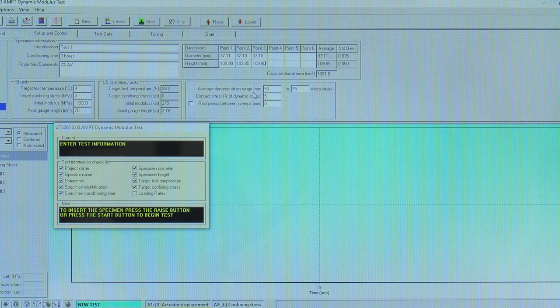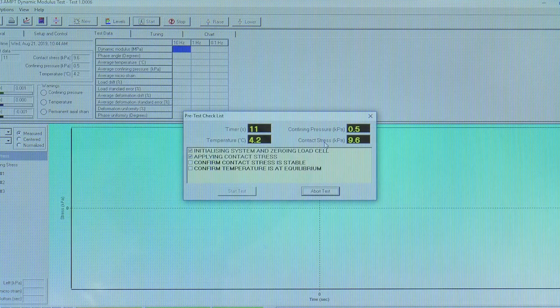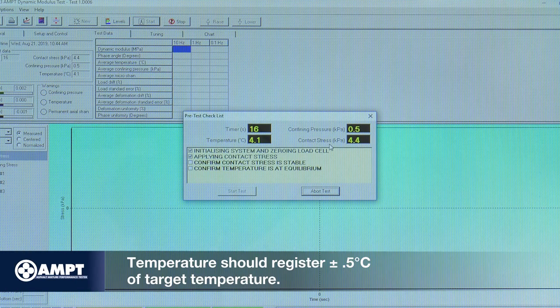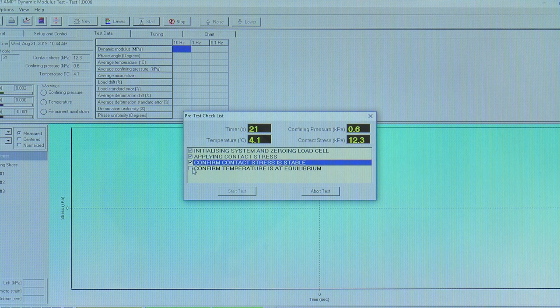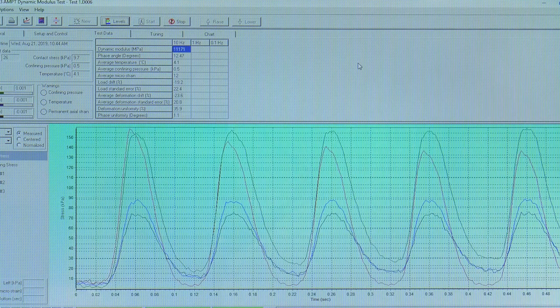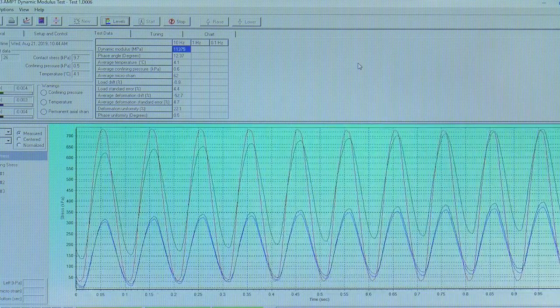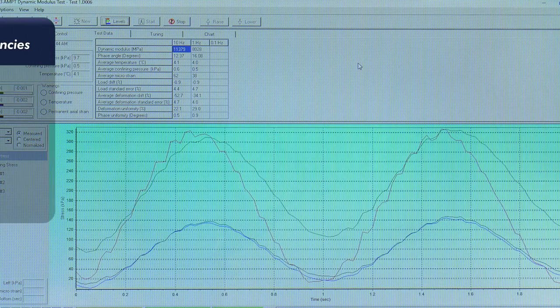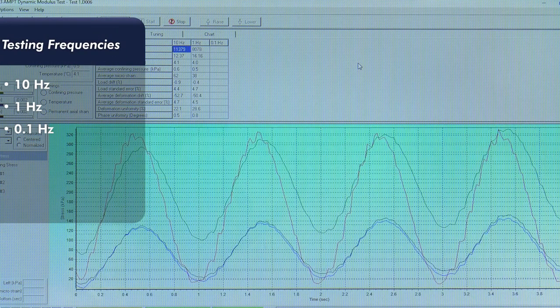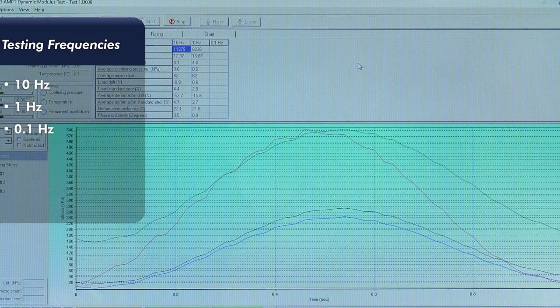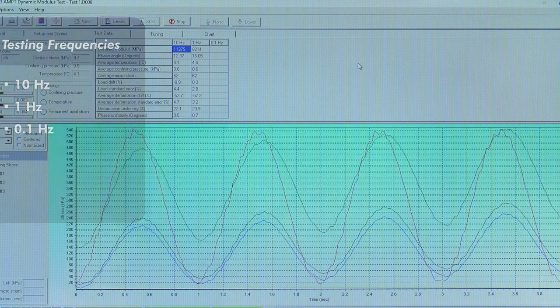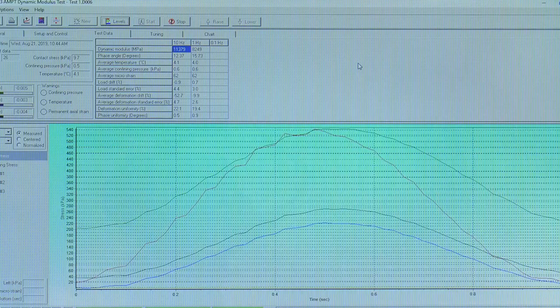Verify the average dynamic strain range is between 50 and 75 microstrain, and the contact stress is 5%. Wait for the contact pressure and temperature to stabilize. The temperature should register within plus or minus 0.5 degrees Celsius of target temperature. Check confirm and then start the test. Begin testing at the lowest temperature and highest frequency. Test all frequencies from 10 Hz to 1 Hz to 0.1 Hz before moving to the next higher temperature. Follow the recommended test temperatures in the standard.